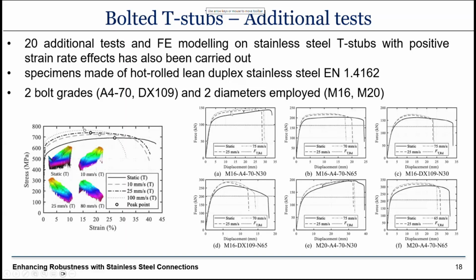And the T-stubs also show that with increasing strain rate, you can get a slight or a higher increase in strength. So we tested T-stubs both with negative and positive strain rate effects. Two bolt grades were considered in these additional tests: the DX109, which is a high-strength stainless steel bolt, and an austenitic stainless steel bolt, A4-70, which has a theoretical ultimate stress of about 700 megapascal. In reality, it's a bit higher than that, more towards 800. And for the DX bolts, the ultimate stress was about 1,140, so about 14% higher than the nominal one. And also two bolt sizes were considered, M16 and M20.